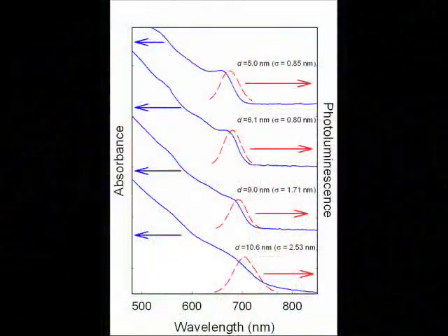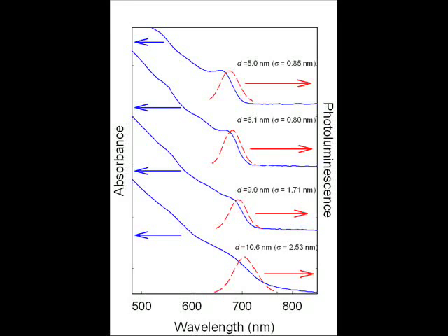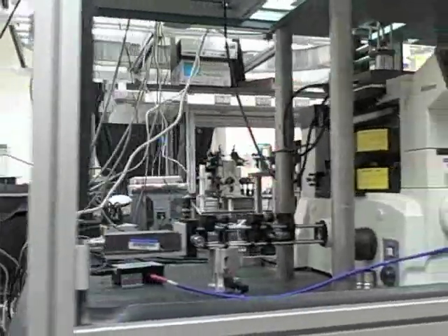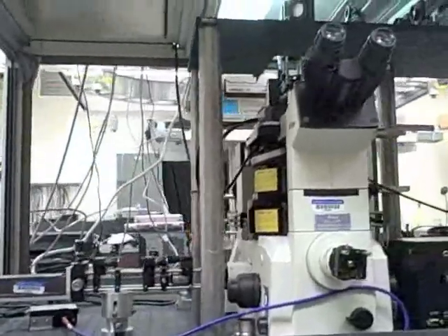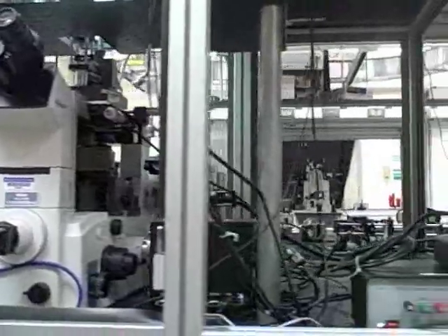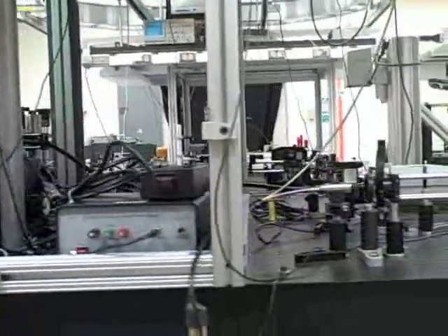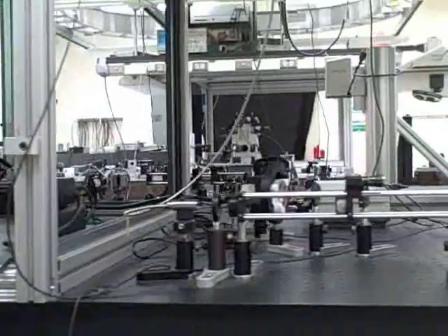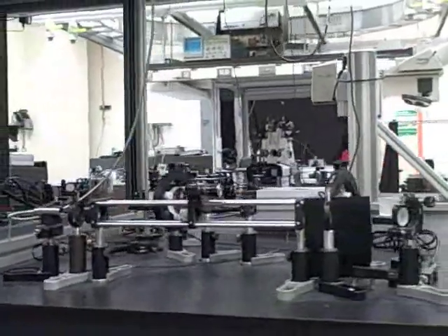From an optical standpoint, nanowires are interesting because their absorption and emission properties can be tuned by varying their diameter. Specifically, ensemble measurements reveal that as nanowire diameters decrease, a blue shift in their onset of absorption occurs with a corresponding blue shift in their photoluminescence peak. To determine the absorption and photoluminescence properties of individual semiconductor nanowires, we use single-molecule microscopy and spectroscopy. These techniques allow us to perform confocal imaging, epi-illumination, and emission spectroscopy on single nanowires such as cadmium sulfide and cadmium selenide.